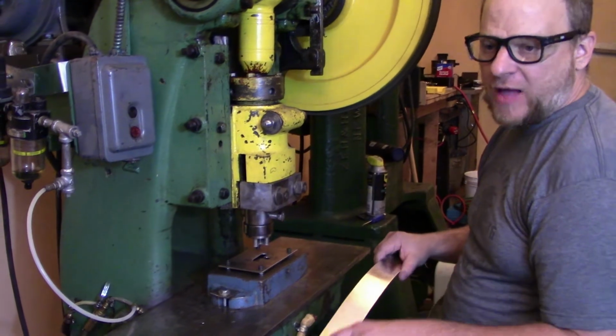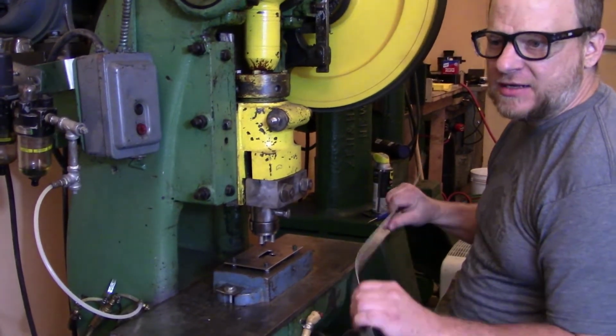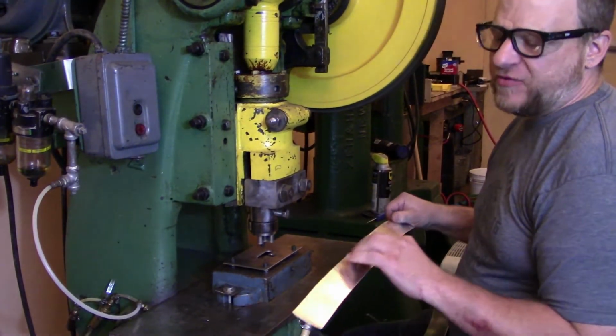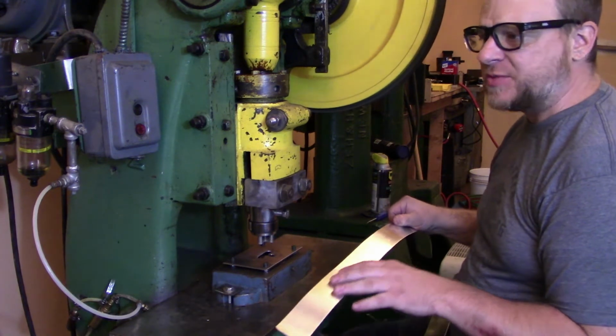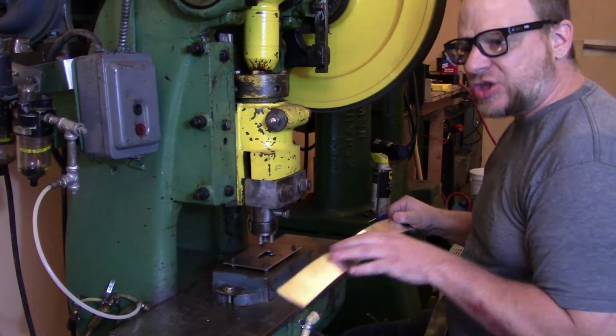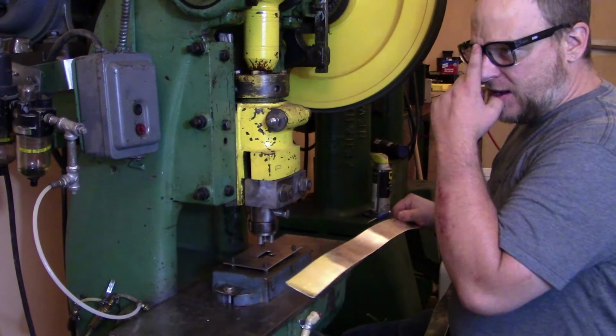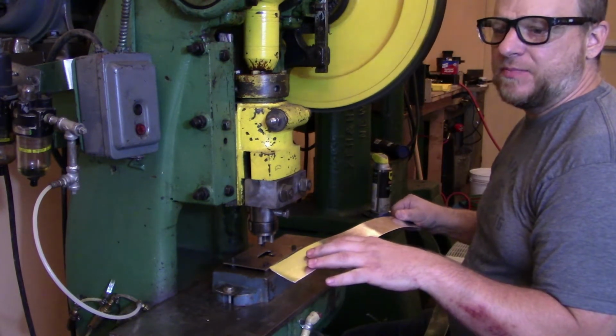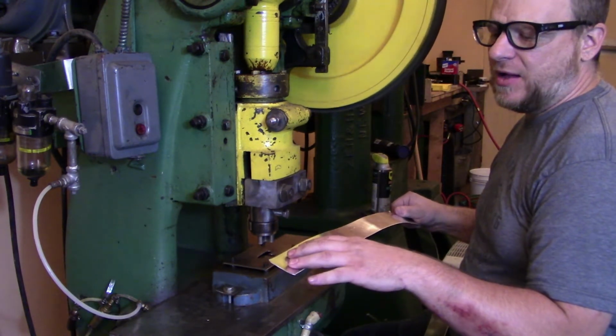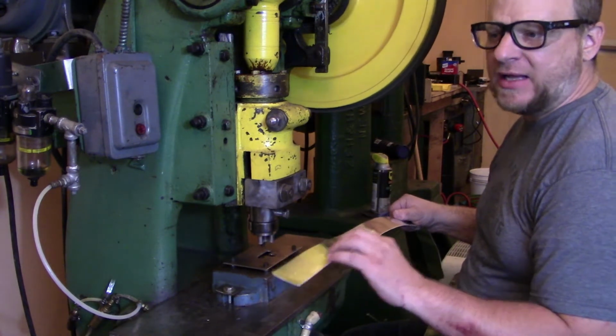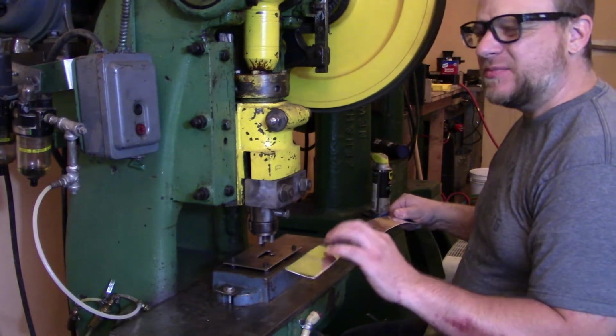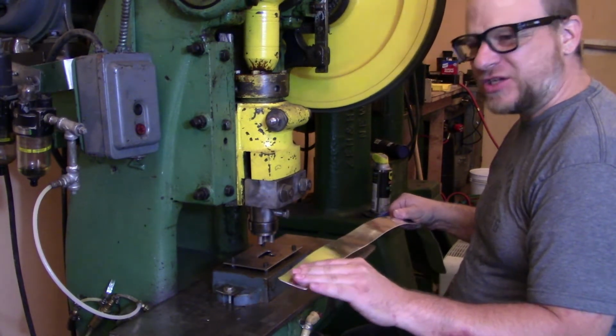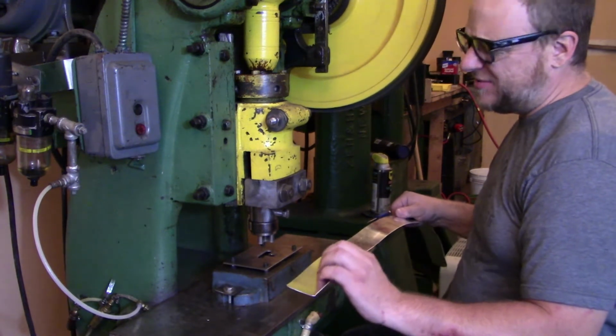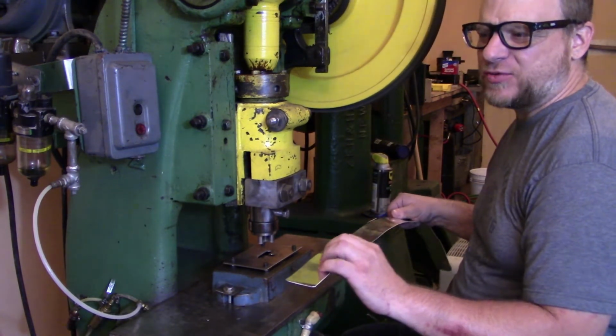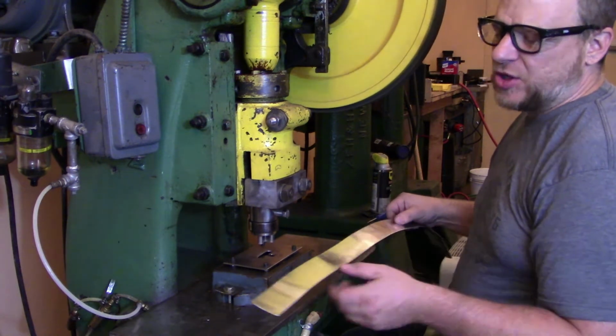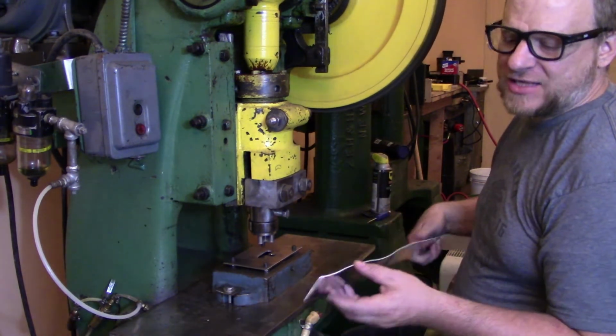I take this material as rolled because it's going to have a lot of hardness to it. If you were to blank your precious metal dead soft or fully annealed, you can run into some deformation, what we refer to as cupping. And so you can get some inconsistent blanks, you can get a lot of extra flashing, you can get just some little extra trouble when it's super soft because it's real malleable and it changes shape. So I like to do it as rolled.